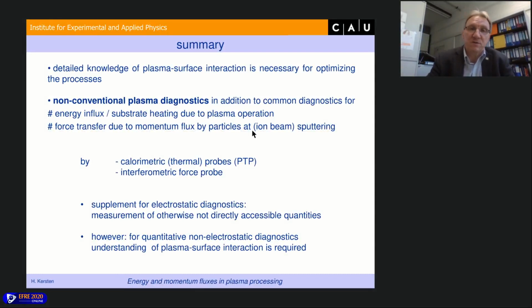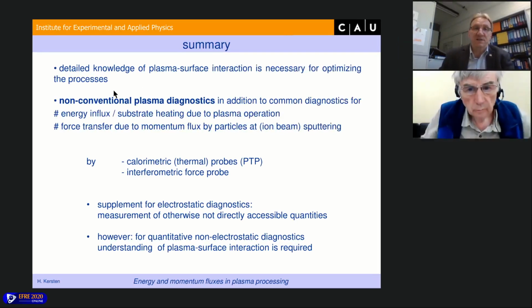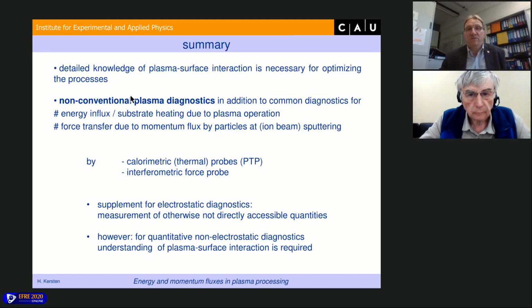I would say that, of course, if you want to change surfaces, if you want to deposit films by sputtering or by PECVD, you have to know something about the plasma process. You have to diagnose the plasma process for optimization. And in addition to the common diagnostics, it is important to have some non-conventional diagnostics like these calorimetric or thermal probes, or like these force probes. They are rather simple, and you can get a lot of information, especially also on neutral particles, on the flux of the neutral particles. But of course, this can only be a supplement in addition to the common diagnostics, Langmuir probes and spectroscopy and so on. But it can be very helpful to get more insight, to get more information about the plasma surface interaction.